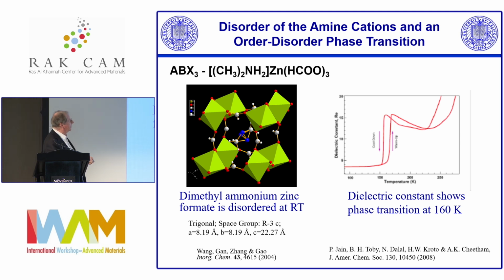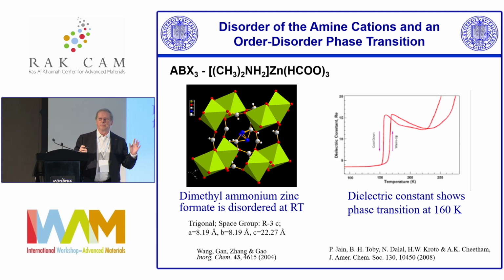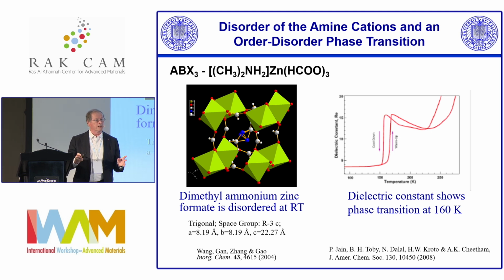So we did dielectric constant measurements first of all, and also some low-temperature diffraction, and showed that indeed there is a phase transition there. And initially, we didn't dare to say that it was a ferroelectric because we didn't have definitive evidence. And I had a colleague in Cambridge who made a living out of proving that most people's ferroelectrics were actually anti-ferroelectrics.